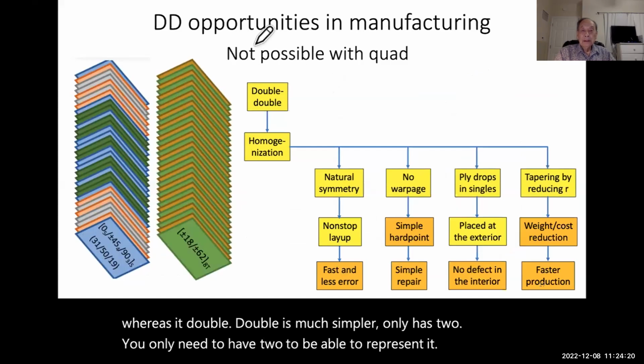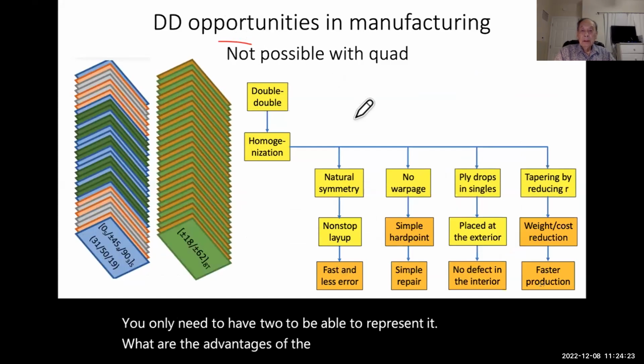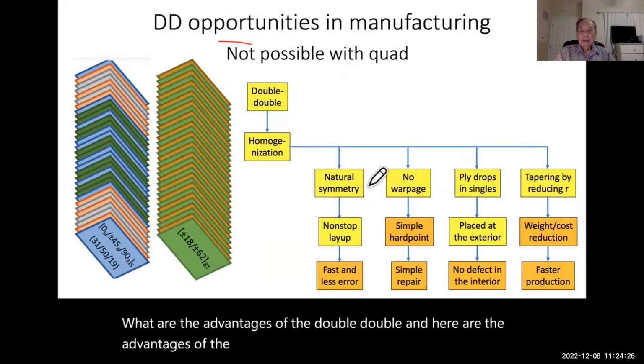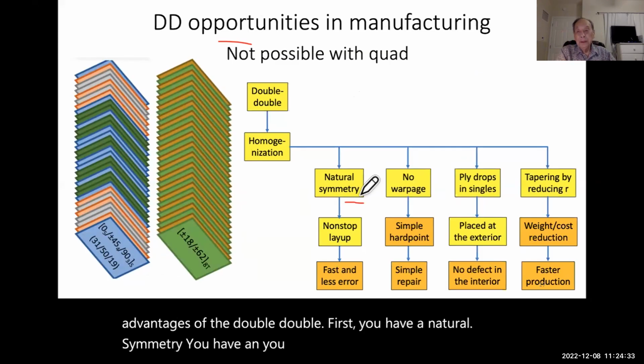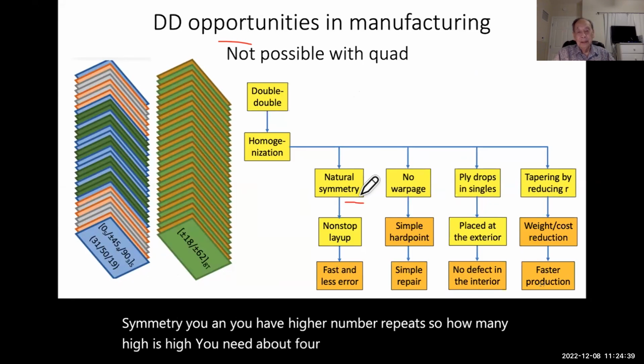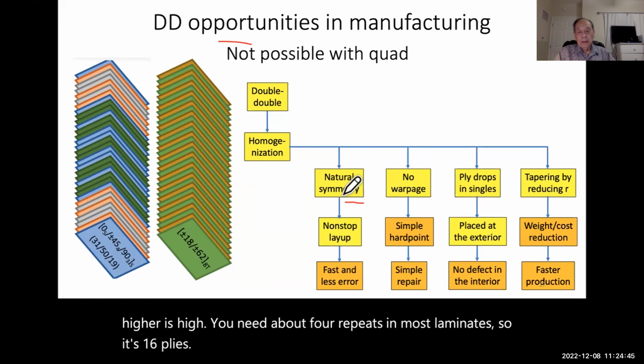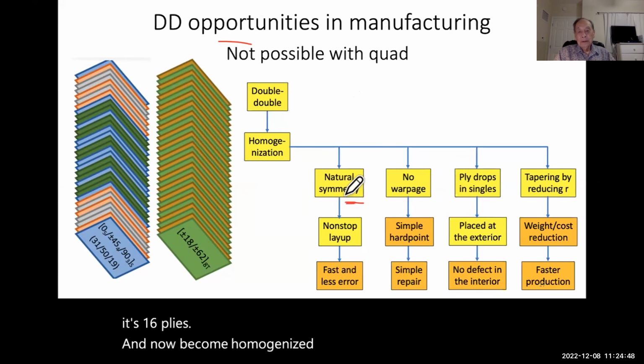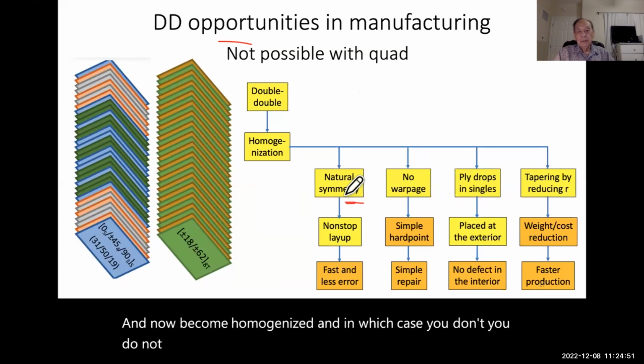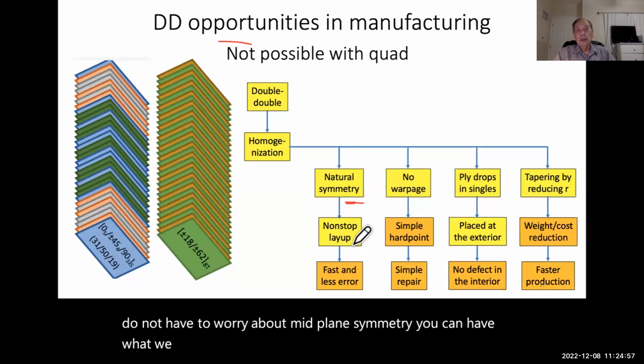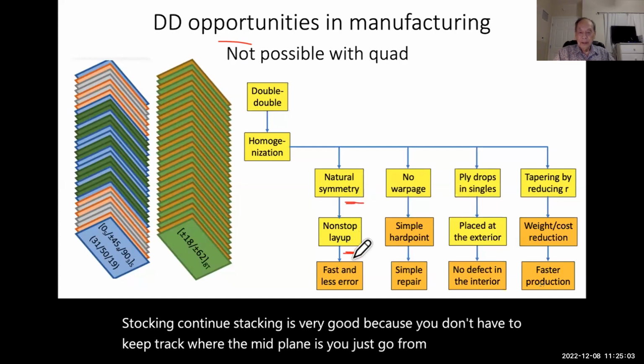So what are the advantages of the double-double? And here are the advantages of the double-double. First, you have a natural symmetry. You have high enough repeats. So how high is high? You need about 4 repeats in most laminates. So it's 16 plies, and that will become homogenized. And in which case you do not have to worry about mid-plane symmetry. You can have what we call continuous stacking. Continuous stacking is very good because you don't have to keep track of where the midplane is. You just go from one end to the other.